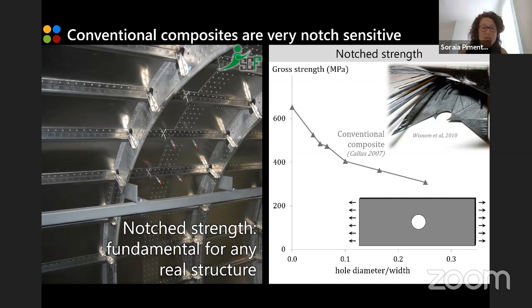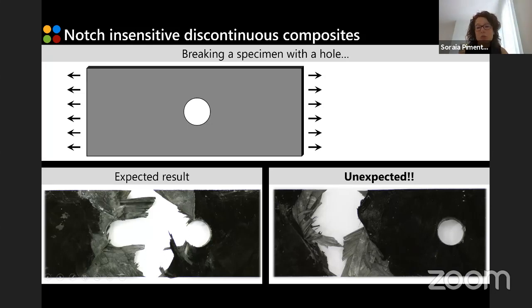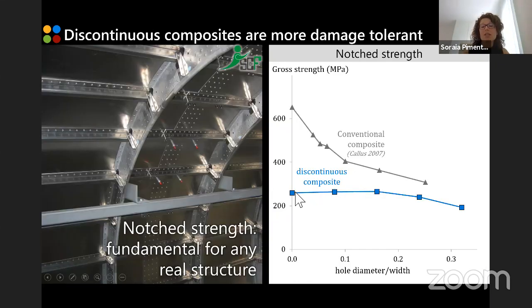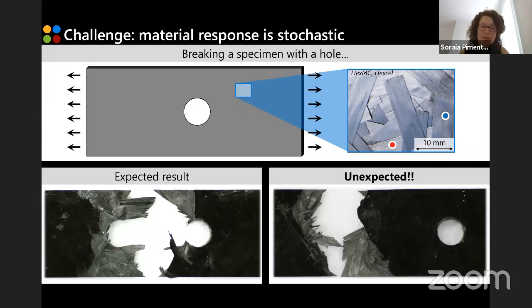So when we do notched tests, with a geometry that you can see here on the top, with the discontinuous composites that I mentioned in the previous section, sometimes we do see that failure happens near the notch, as we would expect with conventional composites, but other times we actually get failure away from the notches. So basically the material seems to be insensitive to the presence of notches. And if you think about the notched strength, you can see that the strength of these materials is much less affected by the presence of notches compared to a deep reduction of notched strength for conventional composites. So this is, of course, very good news. So we can say that these materials are the ultimate notch insensitive material.